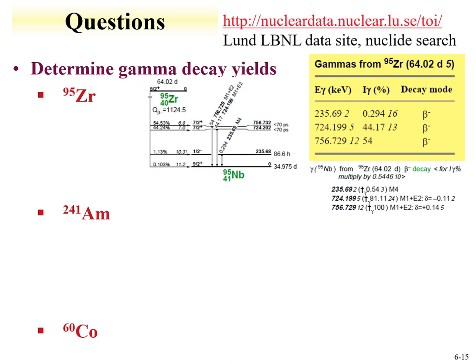What this looks like, this is from the table of the isotopes, is our gamma decay scheme, where we have the zirconium-95 decaying by beta. 54% of the time it populates this state, 44% of the time it populates the lower lying state. You see these are both 7/2 states. Zirconium-95 is 5/2 plus, so decaying to a 7/2 plus, very reasonable decay. We can even see the log ft values here, relatively low, spin change of 1. From what we learned in beta decay, these are common transitions.